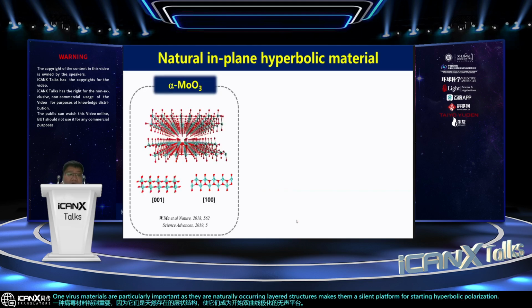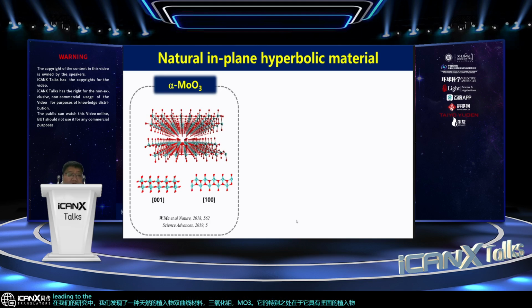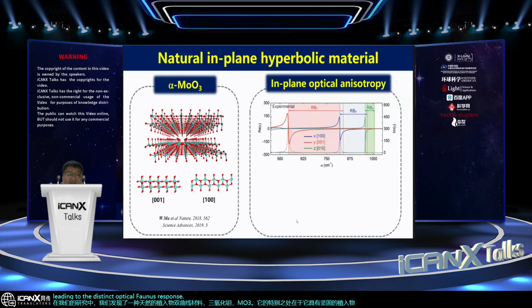In our research, we discovered a natural in-plane hyperbolic material, molybdenum trioxide, MoO3. What makes it special is that it has strong in-plane anisotropy, leading to distinct optical phonon responses in different in-plane directions in the mid-infrared region. This results in a situation where the permittivity can have different signs within the same plane. So what is the significance of this discovery?